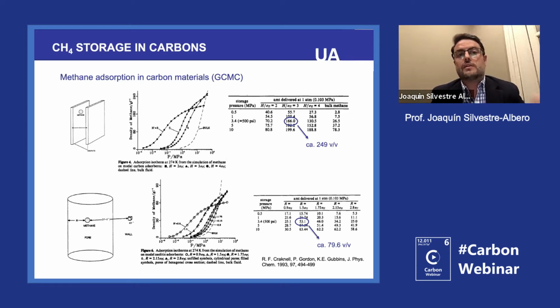So these results were anticipating that with carbon materials, it will be very difficult to achieve the DOE target at 3.5 megapascals, but you must be able to do it at 10 megapascals.